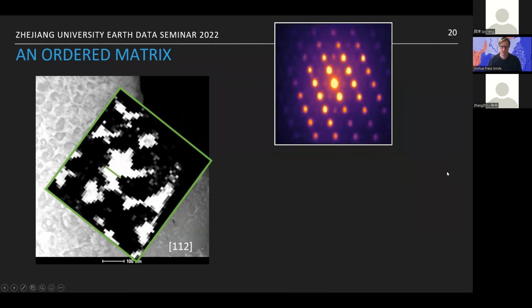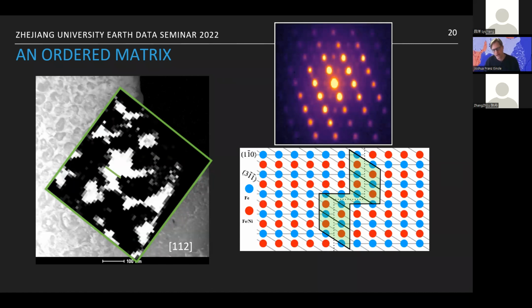Digging back to some literature from the 60s on binary alloys, in this case originally platinum copper, it was shown that rotations to a superlattice like this are expected when you create what are called antiphase boundaries. What's happening is, as the tetrataenite particles grow and expand, they're trying to push all the nickel into the matrix. But because of coherency, and the fact that certain tetrataenite grains will be at a slightly different orientation than their neighbor, the only way for the matrix to obtain and form a crystallographic structure is to create what,